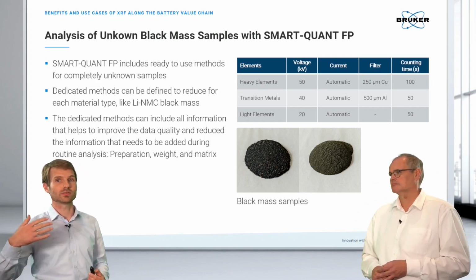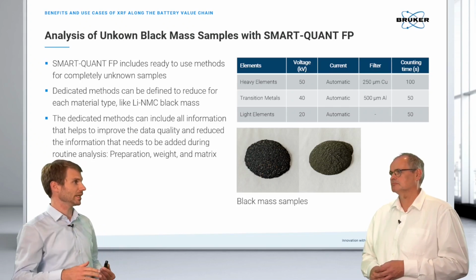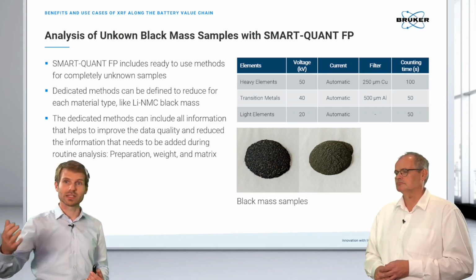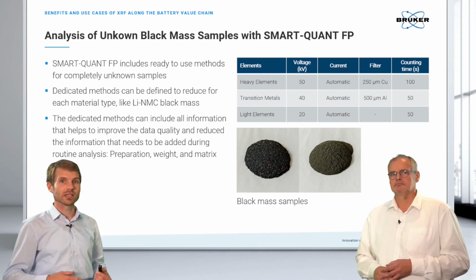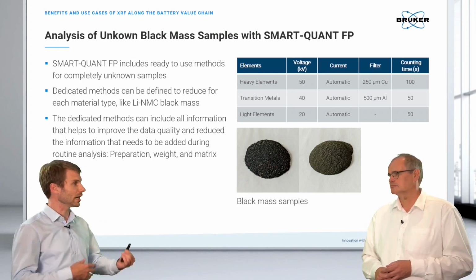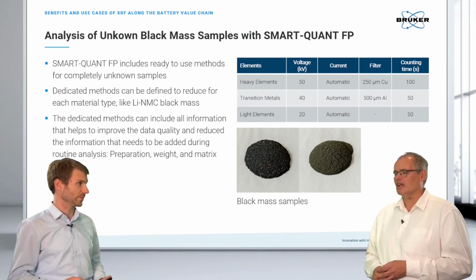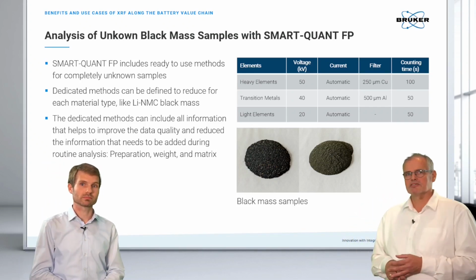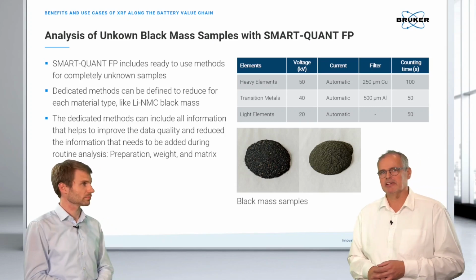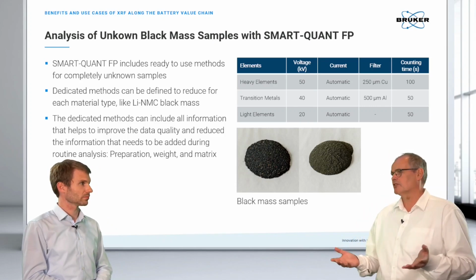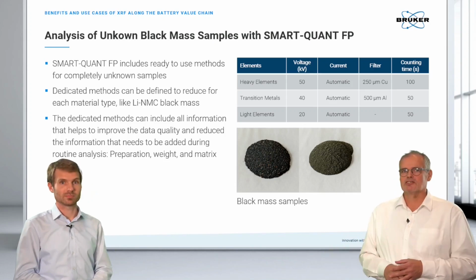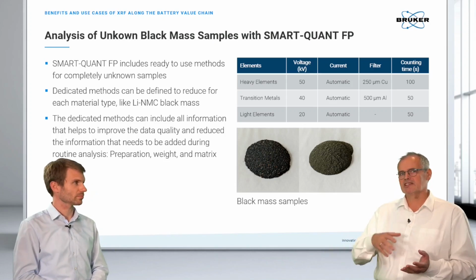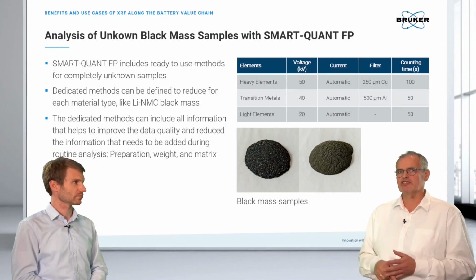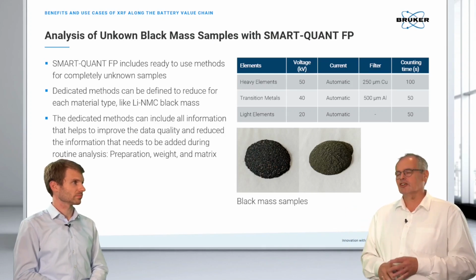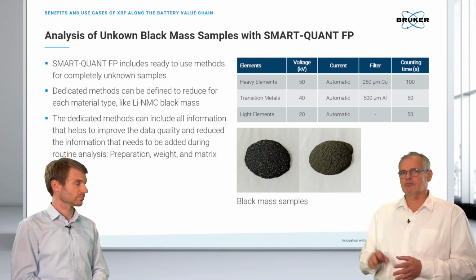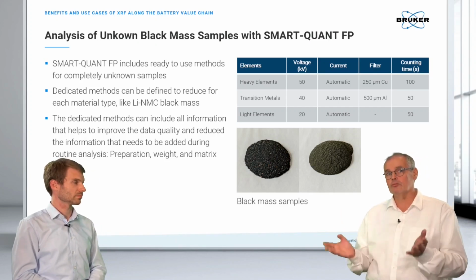But overall, the system really provides you the guidance of what to use. For example, to use rather low excitation voltages for light elements. It provides the best selection for the filter and also gives you a first indication about the counting times you should use. The difficulty in those recycling applications is that we typically don't have any calibration material. So SmartQuant is the way that you can set up the method and use the calibration behind SmartQuant in order to make your own calibration and store the information in your own method.